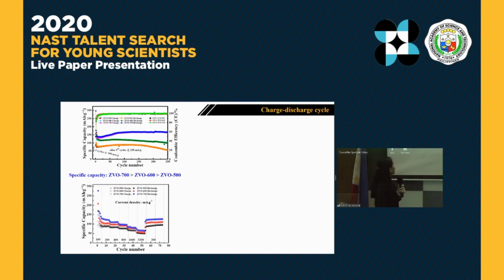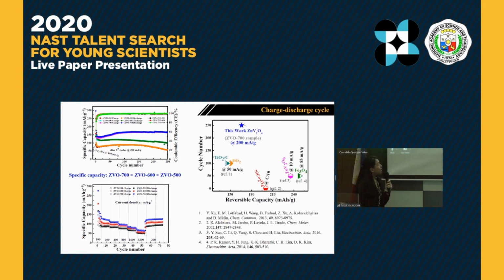Based on our result, we found that as the calcination temperature increases, the capacity also increases. This can be attributed to the higher surface area of the produced nanoparticle. In comparison with other studies, this work, the porous ZnV2O4, has higher capacity compared to that of the other materials, which makes it a good anode material for sodium-ion battery.